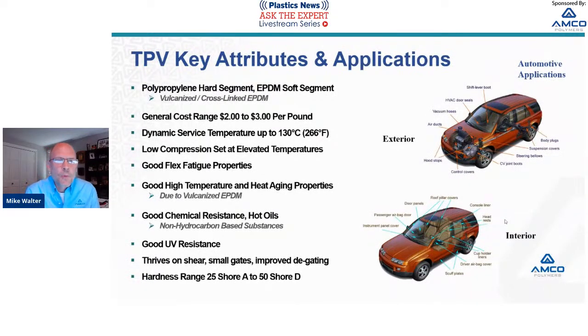Next, we're going to talk about thermoplastic vulcanizates, or TPVs. They have a polypropylene hard segment and an EPDM rubber soft segment. Not to get too far into the technology here, but basically you're combining polypropylene with an EPDM powder, and during the compounding process, the EPDM vulcanizes and becomes fully cross-linked, which leads to some very unique properties for a thermoplastic elastomer.